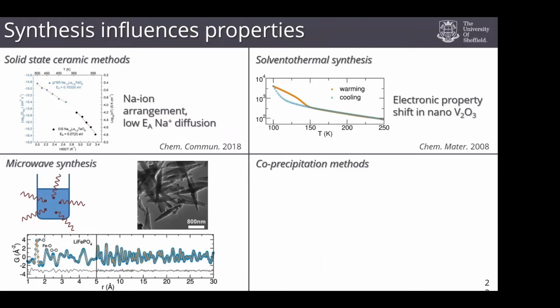So in effect, what it means is your whole reaction heats at the same rate, so you have no temperature lag across it. So I get a lot more control over my reaction, less chance of atoms being really naughty and sitting in the wrong spot. And that's what this is showing you. This sort of experiment here is telling me that the atoms that I'm expecting to be in the lithium layer are in the lithium layer, and the ones I want in the metal oxygen layer are there. They haven't swapped places. If I do this reaction not using microwaves, that's not the case. I get lots and lots of disorder.